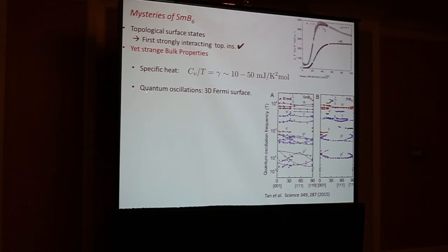But you do see oscillations, and they seem to be best analyzed by analyzing them as bulk oscillations with a bulk Fermi surface. So there's some disagreement on this between the different groups. I can't show you the most up-to-date data because it's not yet published and you're filming it, but I assure you that data shows that this Fermi surface is extraordinarily three-dimensional.